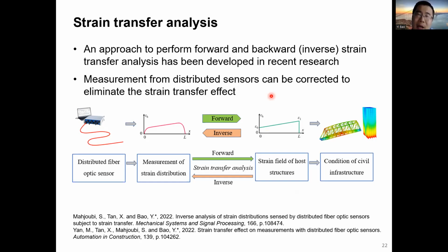We can apply the strain field as the boundary condition to solve the governing equation for the strain distribution in optical fiber. But in real applications, the problem is the inverse problem because we do not know the real strain field. What we know is the strain distribution measured from the fiber optic sensor, and we wanted to determine the strain field in the host matrix. So this is the inverse problem.